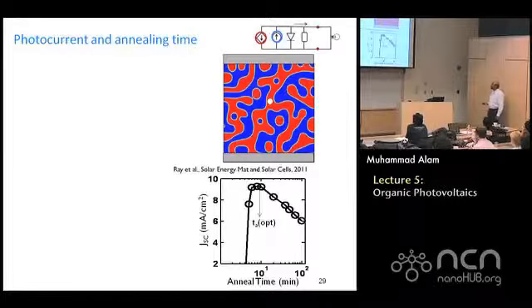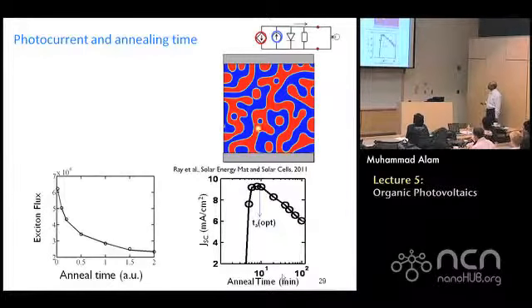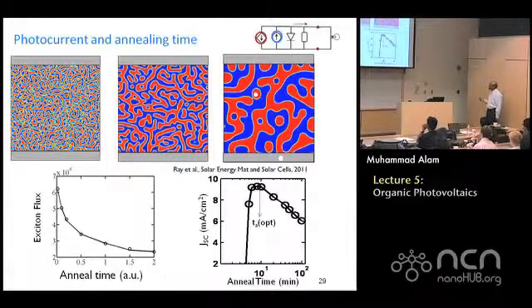The trick is the following. Of course, if this structure is thick, then there is a connected highway that will allow you to go to the proper contact. So this allows you to get out, the holes get out, let's say. But if there are islands like this, which will trap the electrons or holes, then they cannot get out. And what happens in these structures, yes, excitons can get out very easily, but the electrons and holes may not be able to come out through this complicated maze. So you increase exciton dissociation, but you lose out on electron and hole collection, right? And because you lose out on this, that is why there is an optimum.